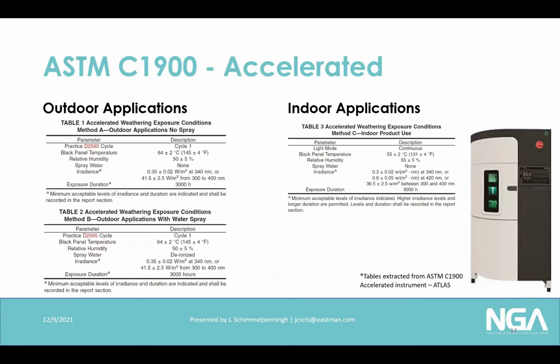These are the tables, and these are taken from ASTM C1900. There are two methods under the outdoor accelerated exposure, and you can see a typical accelerated chamber on the right. These are chambers that are operating with xenon bulbs to simulate sunlight, and the cycles are very, very prescriptive. You have a very tight and high temperature range of 145 degrees F. You have a 50% relative humidity. One has a spray and the other has no spray. And so these are the two accelerated methods.